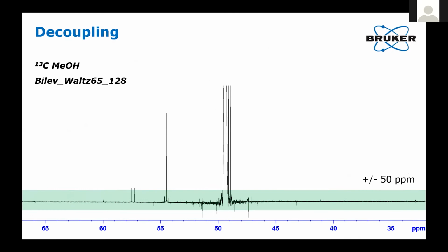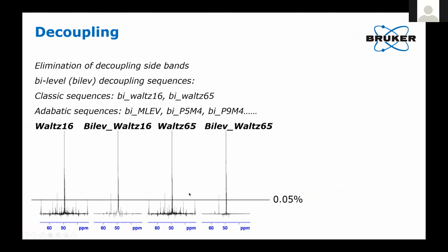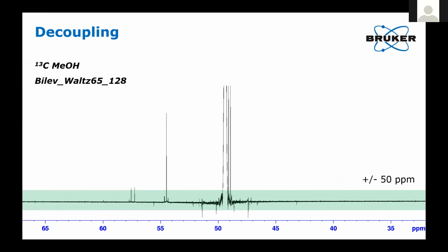So if I blow this up, I'm really at the plus or minus 50 parts per million level, and I can now see my methanol signal. I actually see the natural abundance monodeuterium isotopolog, and I see the impurities in here, and these are well below. I think these little guys here are in the order of about 10,000 to 1 and even lower than that.